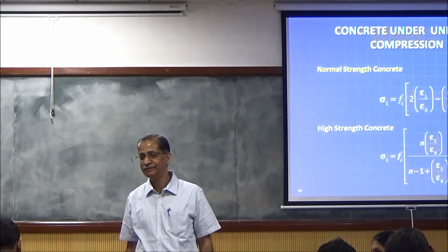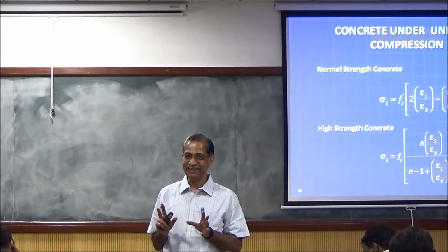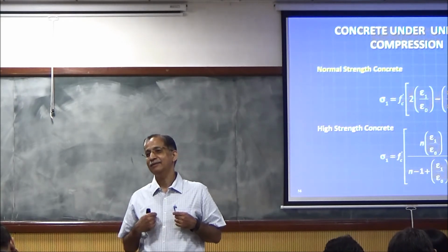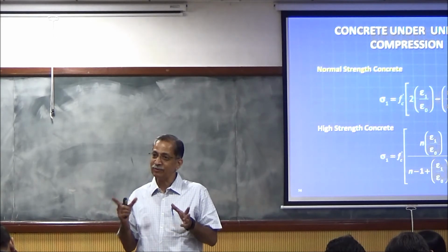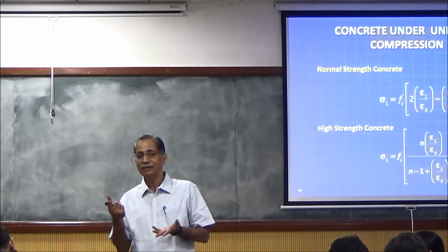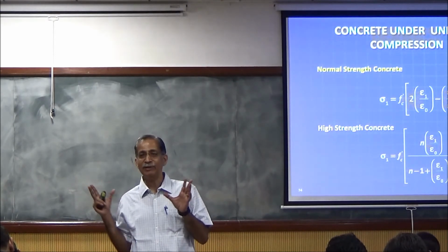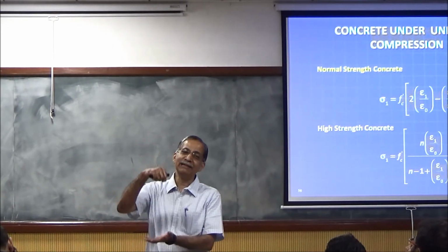So is this called crushing? What is happening? This is not crushing. This is called Poisson's effect. Tensile cracks appearing. But it doesn't fail, it can take more load. We'll see what happens to the Poisson effect when you look at it in 3D. It takes more load, eventually it crushes.